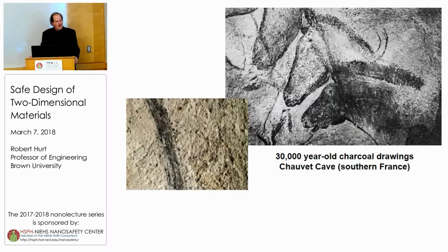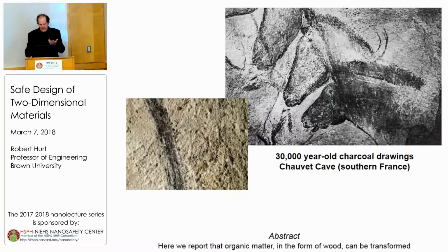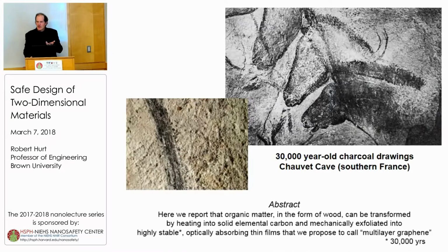So this is charcoal, likely from a campfire, that was mechanically exfoliated onto these cave surfaces. And as a journal editor, I was thinking, if they had submitted this for publication, what would the abstract be? So I took the liberty of writing an abstract for this work. It's here we report that organic matter in the form of wood can be transformed by heating into solid elemental carbon and mechanically exfoliated into highly stable, optically absorbing thin films that we propose to call multi-layer graphene.